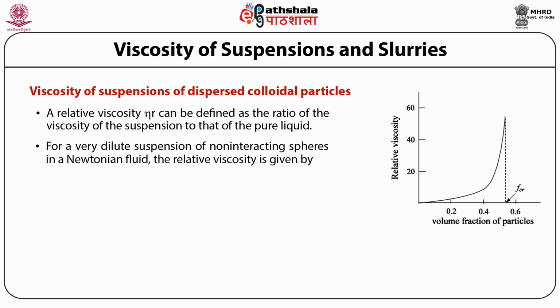Then for a very dilute suspension of non-interacting spheres in a Newtonian fluid, the relative viscosity is given as eta R is equal to 1 plus 2.5 times F, where F is the volume fraction of the particles. The increase in the viscosity with increasing F is caused by the dissipation of energy as the liquid moves around the particles. This equation is known as Einstein's equation. Now, if we talk about non-spherical particles, then the constant in this equation, eta R equal to 1 plus 2.5 F, is more than 2.5. It will not be 2.5.